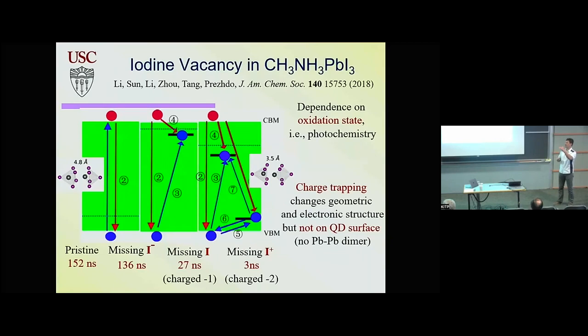In traditional quantum dots that blink, they blink because charges are trapped on the surface and create trap states. So this mechanism, for this particular defect, which is the most common defect, is not going to happen. This actually helps quantum dots to emit better because you don't have charge trapping on the surface.